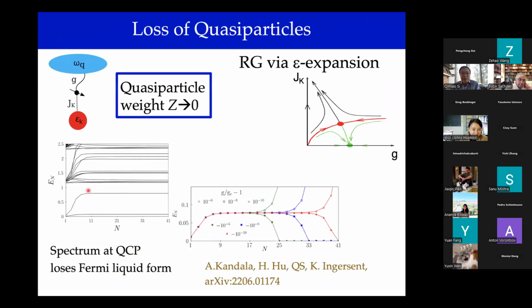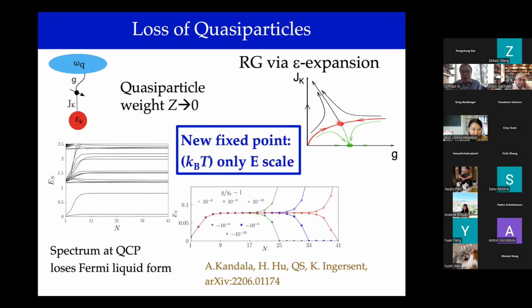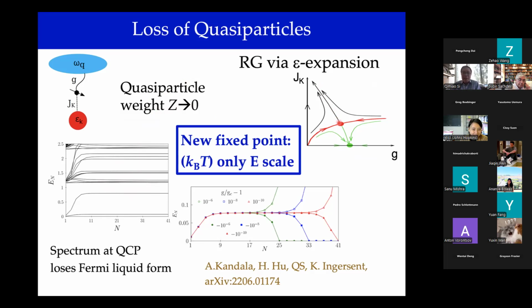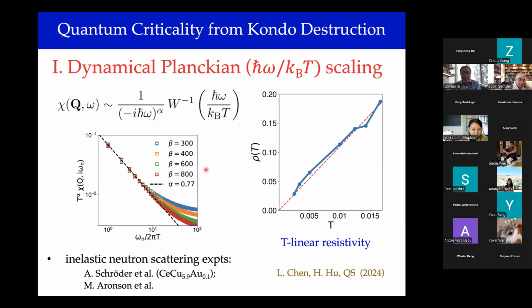And this Bose-Fermi Kondo model realizes a new fixed point, which one can see from some analytical renormalization group calculations and from numerical studies of the finite size spectrum to see that, for example, at this fixed point, the finite size spectrum cannot be described in terms of quasiparticles, and Z has to go to 0. And in fact, this is an interacting fixed point, so that all the microscopic energy scales go away. So there's no room for something like a kBT squared divided by a bare EF scale of the Fermi liquid, because all the microscopic scales have gone away, except for the kBT that's left as the only energy scale for this kind of interacting fixed point. And this allowed us to understand the dynamics data.